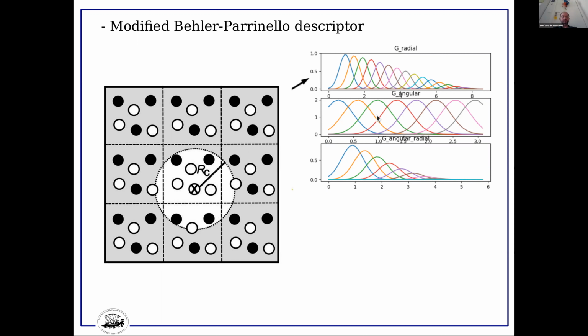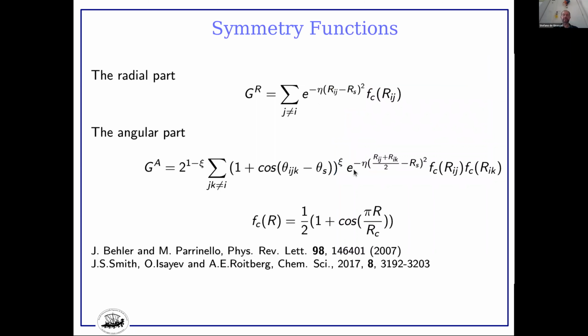discretized pair correlation function for the radial pair correlation function, and a more complicated angular correlation function, and on the basis of these local geometry descriptors, you use this local geometry descriptor as input for your neural network. Okay, so there is this so-called G vector. So these descriptors contain basically radial things that sample the radial distribution function,